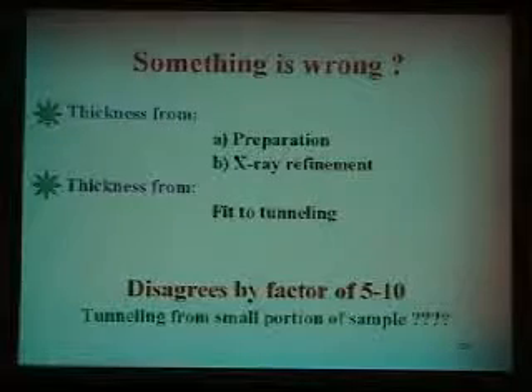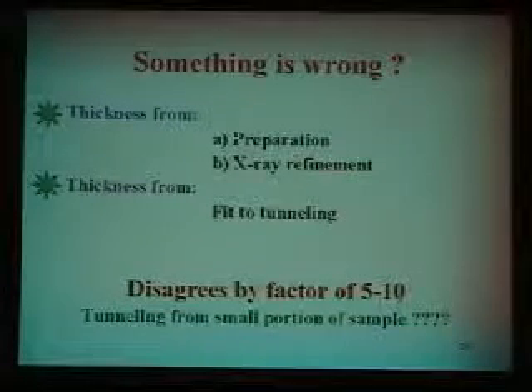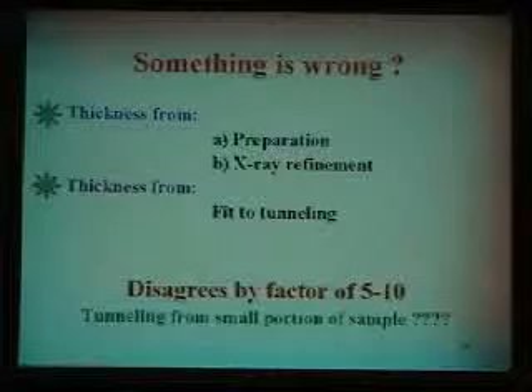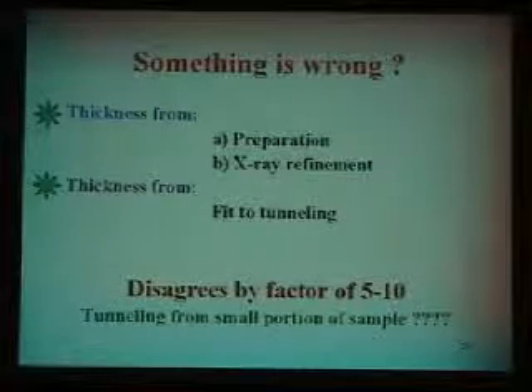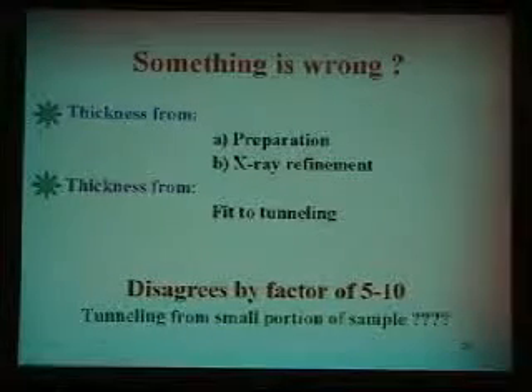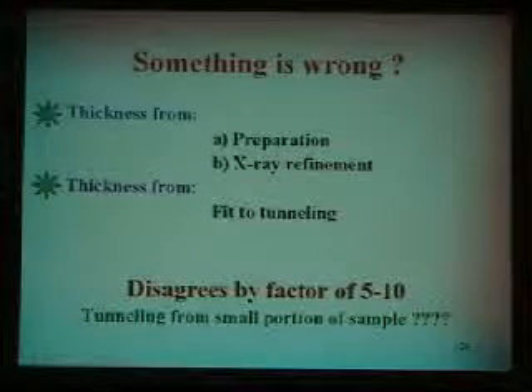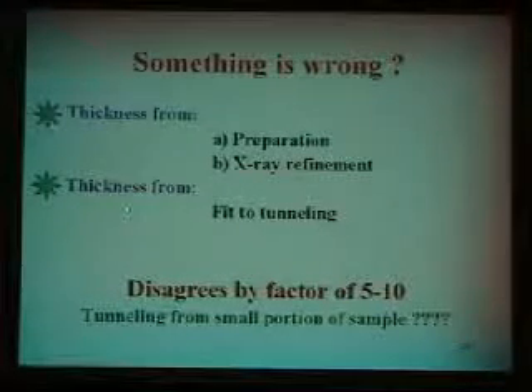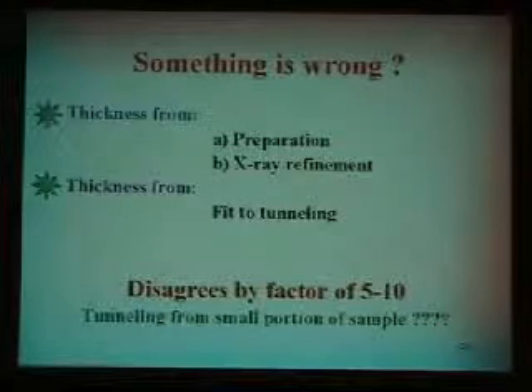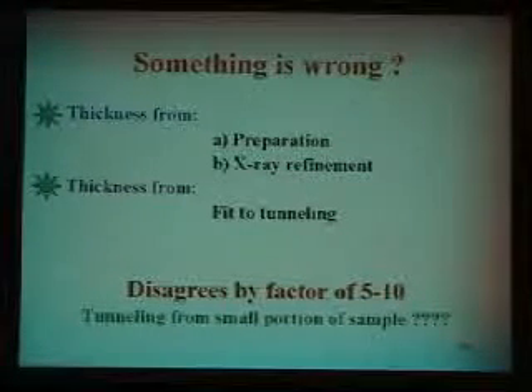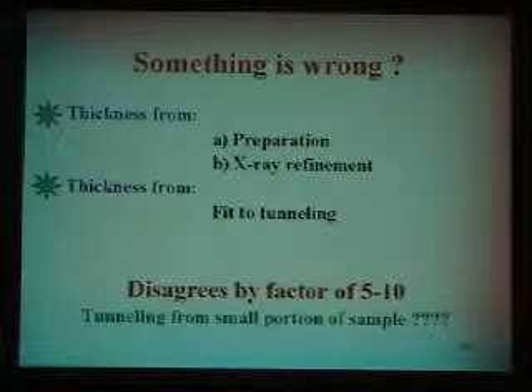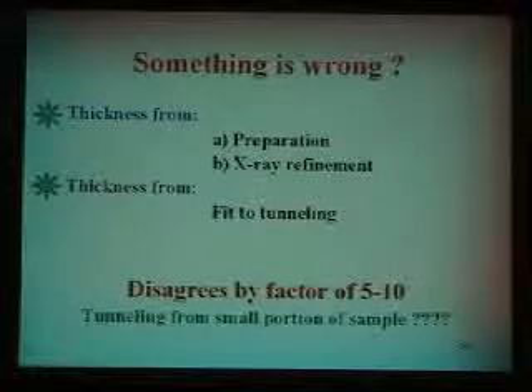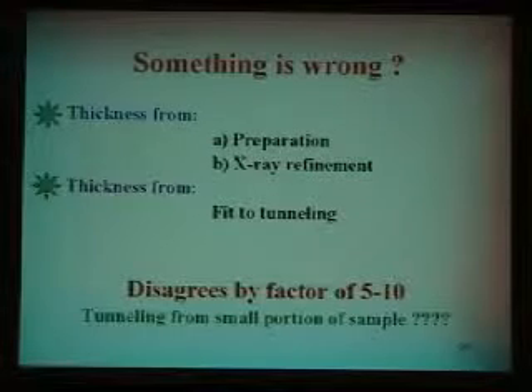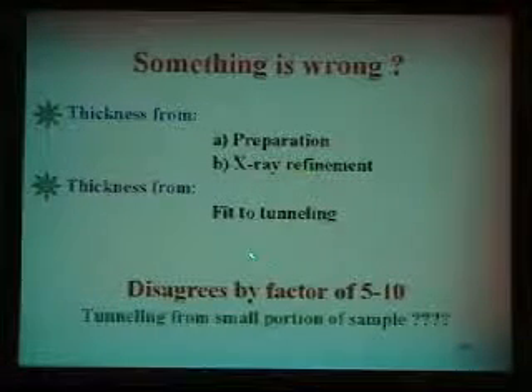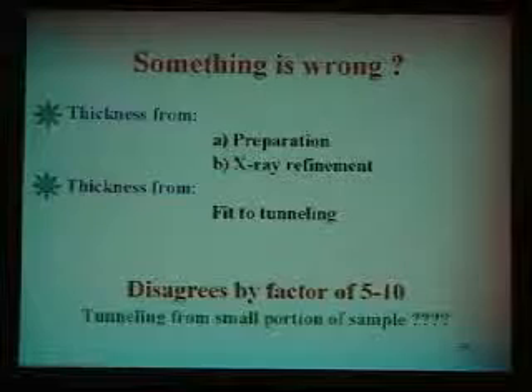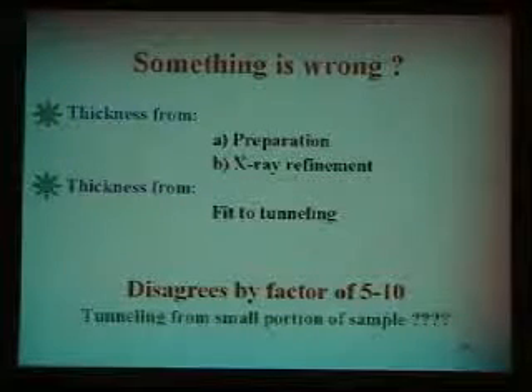The problem we came up with immediately, as soon as we grew this thin oxide, is that if you compare how much material you evaporate, or characterize the thickness of the barrier by X-ray diffraction, and compare that to the fits from tunneling, they disagree by about a factor of 5 to 10. The preparation and the refinement tell me that the thickness of the barrier is 100 angstrom or 300 angstrom. The fit tells me it is only 30 angstrom. So what does that mean?